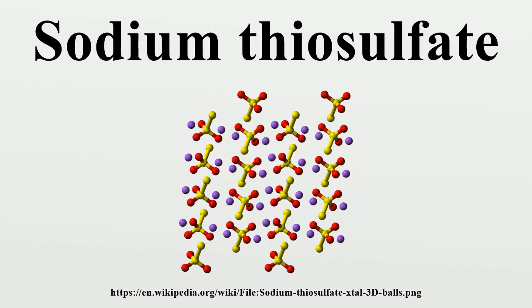The sodium thiosulphate is known as a photographic fixer, and is often referred to as hypo, from the original chemical name, hyposulfite of soda. Gold extraction. Sodium thiosulphate is a component of an alternative lixiviant to cyanide for extraction of gold. It forms a strong soluble complex with gold ions, [Au(S2O3)2]^3-. The advantage of this approach is that thiosulphate is essentially not toxic, and that ore types that are refractory to gold cyanidation can be leached by thiosulphate.